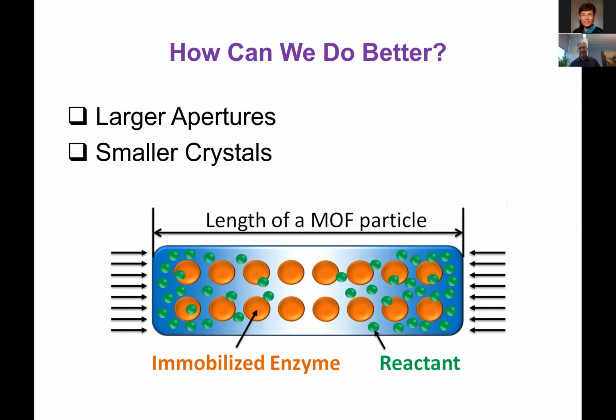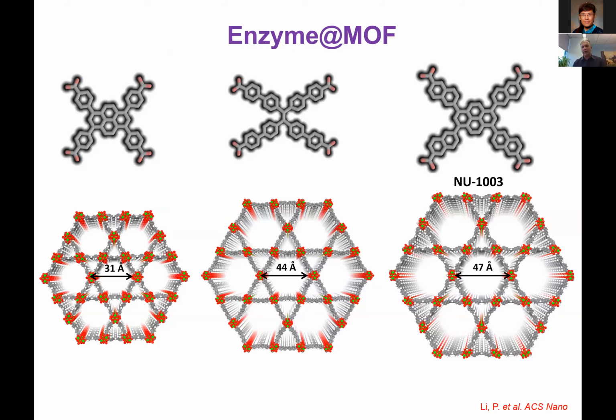The question is, how can we make it better at the initial rate? You could do that by 2 means. One, make those triangles and those windows larger. This way the agent can diffuse faster, or make the crystallite smaller. We went and we tried to do both with this new MOF.